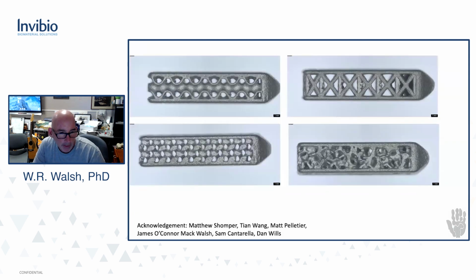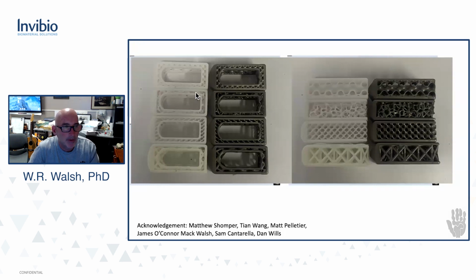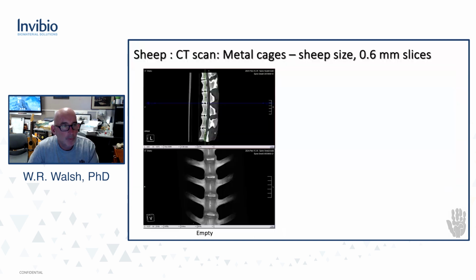So we did another little study, and I have to acknowledge the team on the bottom, including Matthew Shomper, who printed these idealized titanium implants for us, kind of a TPMS system, an organic lattice, a truss, and again, just another lattice structure. And we printed them in titanium. But then when we got the models, we printed them in PLA because we have a PLA printer. We don't have a bone printer yet. And we printed them. And what we did was we took those implants and put them into the sheep spine, and we CT scanned them with 0.6 millimeter slices. So even potentially a little bit better than clinical CT scans.